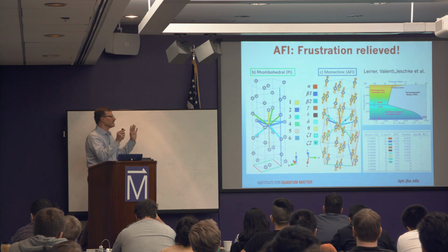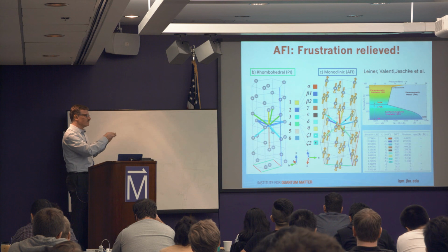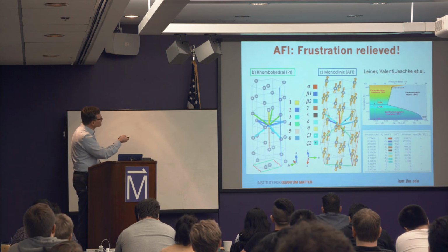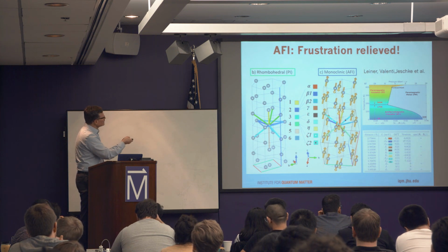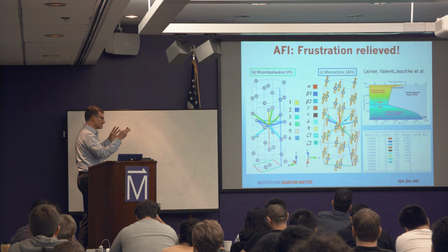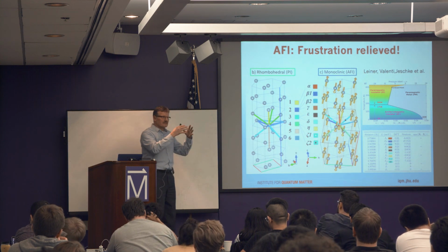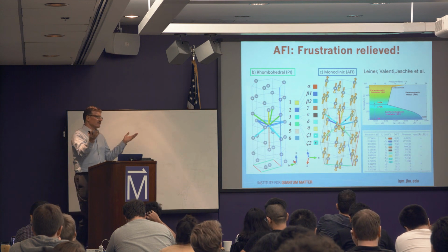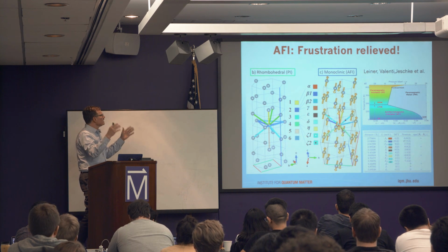And that really contrasts with the situation in the paramagnetic insulating state where I had this competing near and next neighbor interaction. So what's happening, we think, at this transition is that I'm going from a very frustrated arrangement of interactions, which does not point to a specific ordered magnetic state and produces this very, very disordered configuration of spins in the paramagnetic state.